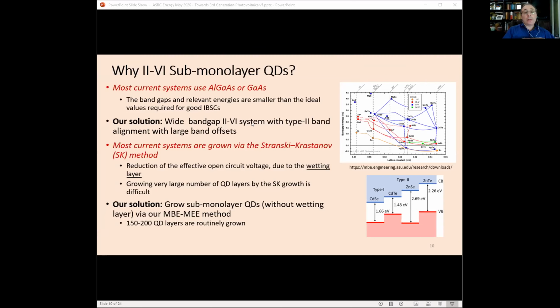And it turns out the quantum dots we work with, so-called submonolayer quantum dots, are grown without a wetting layer. And we successfully showed before that we can grow close to 200 layers, and probably we can grow thicker than that. So that's why we started looking at the application of these quantum dots to fabricate successful solar cell devices.